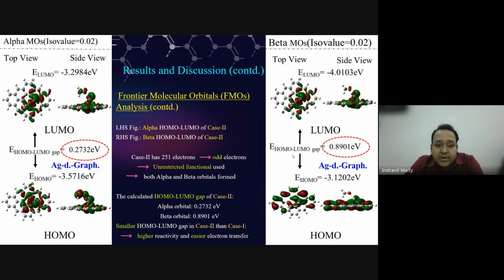In the second case, where silver doped graphene has been considered, it has been observed that the total number of electrons is 251, which is odd, so the unrestricted functional was used, which gives alpha orbital as well as beta orbital, where alpha orbital denotes the up-spin category and the beta orbital denotes the down-spin category. And here the gap between LUMO and HOMO in the case of the alpha orbital is 0.27 electron volt. And on the right side, which denotes the beta molecular orbital, the band gap was 0.89 electron volt.